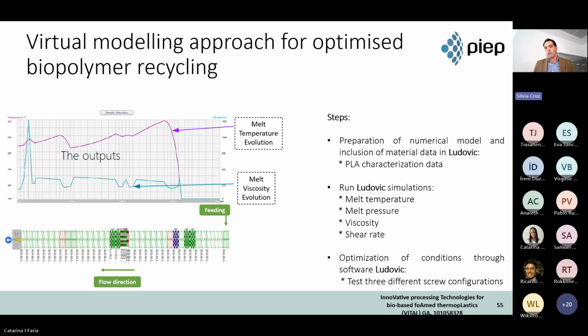So we get melt temperature evaluation, melt viscosity, melt pressures, shear rates. We get all this data from what's happening inside the extruder, and we can anticipate if there is some degradation, if there are some temperature levels that are reached that we need to avoid. And with this, we can optimize both the processing parameters on the compounding and also the screw configuration, the barrel configuration.